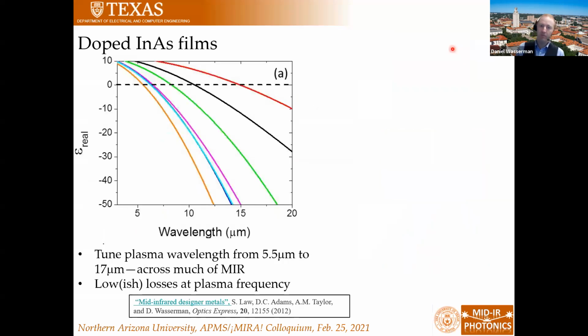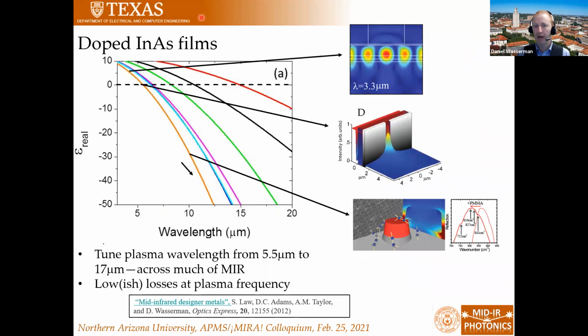So what does this mean? Well, it means that we can epitaxially grow metals with properties across the mid-infrared that give us all the sort of things that we want to be able to do. Namely, if we lightly dope, we can tune the refractive index without turning it into a metal. We still have a positive permittivity. We can cross over from positive to negative permittivity, and this would be our epsilon near zero. And then we have this range here where we have permittivity that is on the order of what the surrounding dielectrics would be, where we can exhibit plasmonic response.